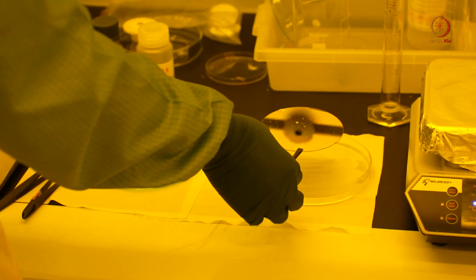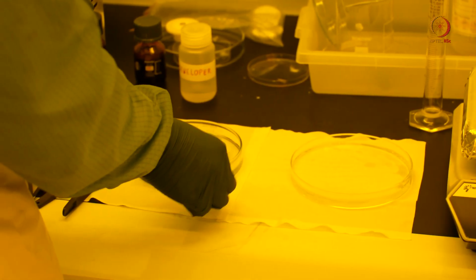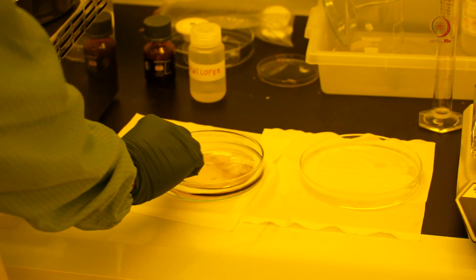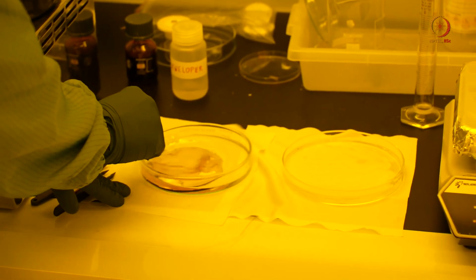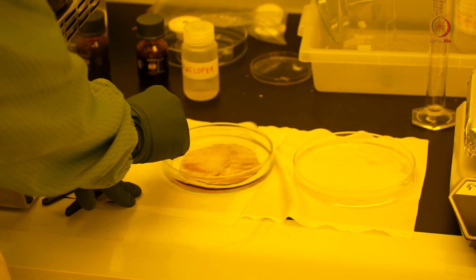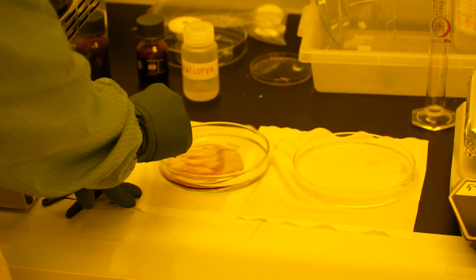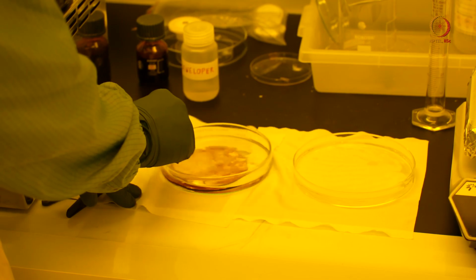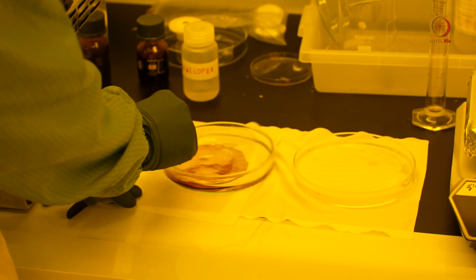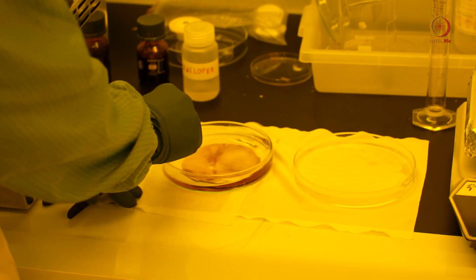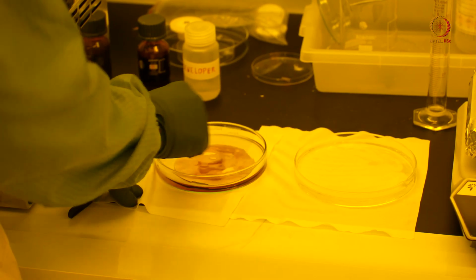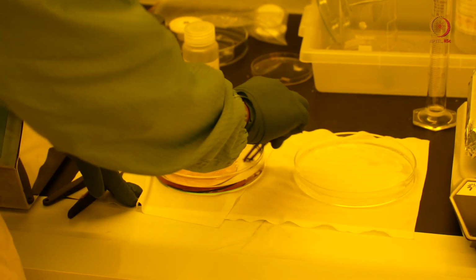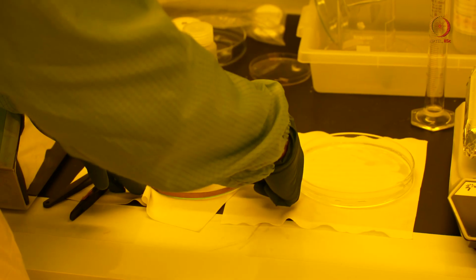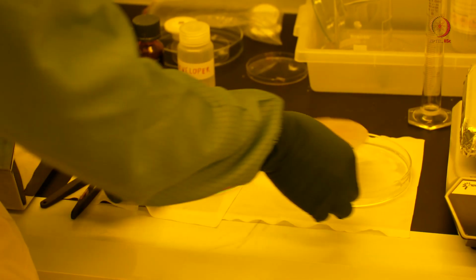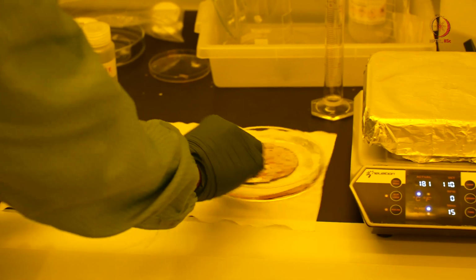So I'm moving the wafer here from DI water to the developer, and you can see some color changes that will happen. So that is the excess photoresist being stripped off. This process will take around 20 seconds. So I'm just taking out the sample to see if the exposure development has been completed, and I'm shifting it to DI water.